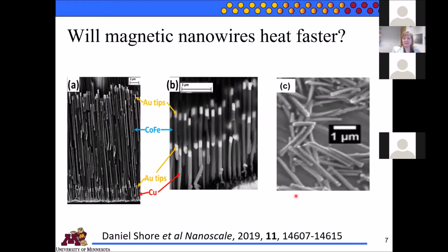So the question really is, will magnetic nanowires heat faster than the particles that are right now being used? So my student and I have this paper with John Bischoff's group where we investigated this. What I'm showing you here are a series of magnetic nanowires. These are very long cobalt iron with gold tips. We grew a little bit of copper at first just to help the growth, and then we break them off, separate them from the template, and that's what they look like.